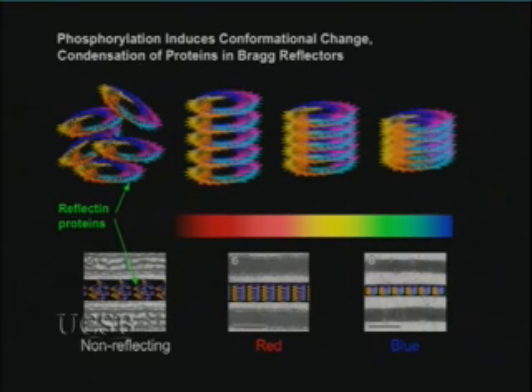What we've discovered recently is that the molecular switch governing this change results in the activation of an enzyme that catalyzes the addition of phosphate groups onto a protein that is a key constituent in the reflective microscopic structures in those cells. We call those structures Bragg reflectors. And our hypothesis is that the phosphorylation of the protein changes its conformation and its hierarchical assembly, driving the condensation of these Bragg reflector plates and thus changing the optical properties.